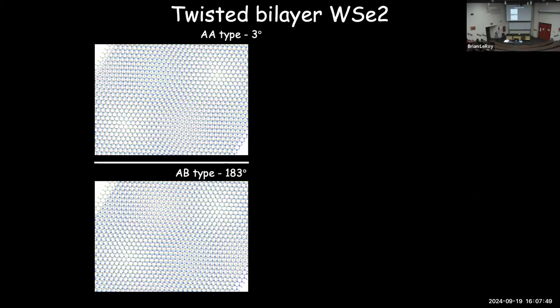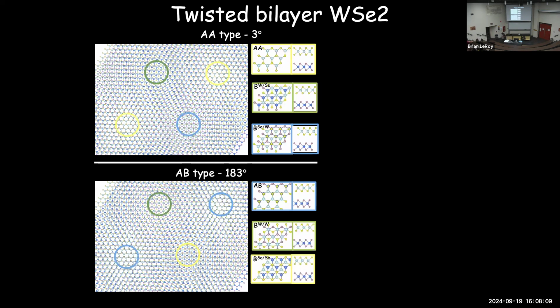So let me look now at AA-type stacking. That means a 3-degree twist angle between the layers. And then this 180-degree rotation version of it, which I call the AB type, where we've rotated 183 degrees here. On here, they probably look identical to you, and they are, except for the microscopic stackings. In this case, we have states which have AA-type stacking directly on top of each other. Here we have ones which are the AB-type stacking.